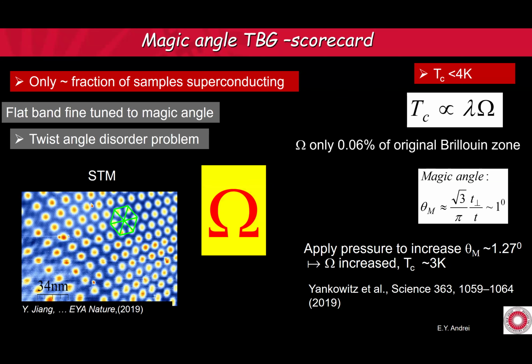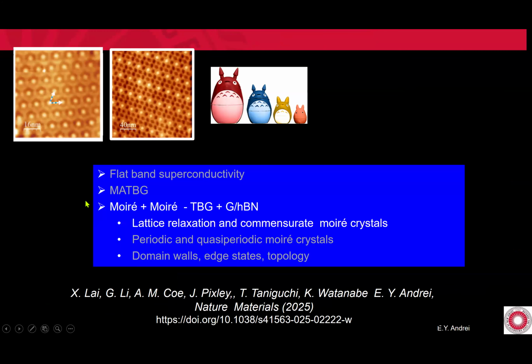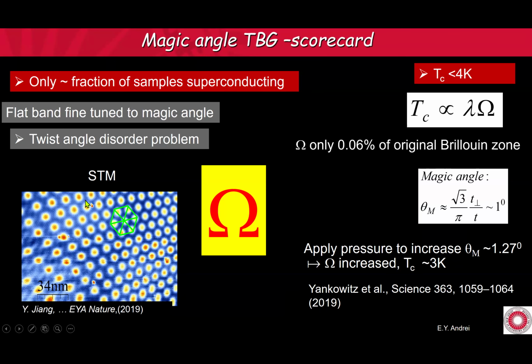Okay, so I think the kicker is here, maybe we have to increase the volume of the flat band. Back to my original point: even on the perfect magic angle quasiperiodic graphene, if you do a band structure calculation, it's not flat. It's not infinitely flat, but this is not the kicker. The kicker, I think, is the volume in reciprocal space, which is much too small. Maybe if it's flatter, it would be higher. I don't know. Perhaps.